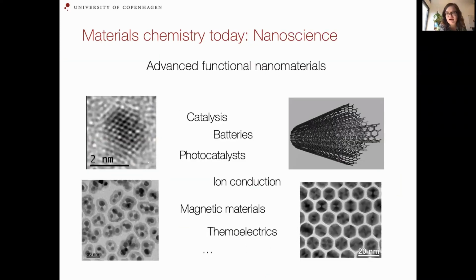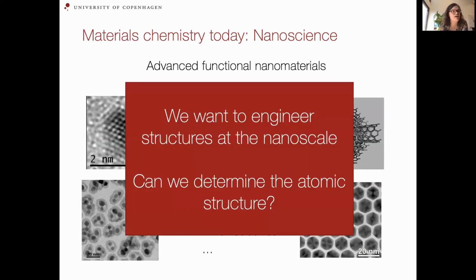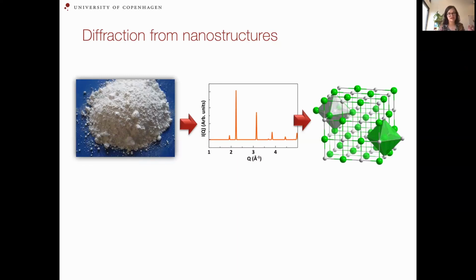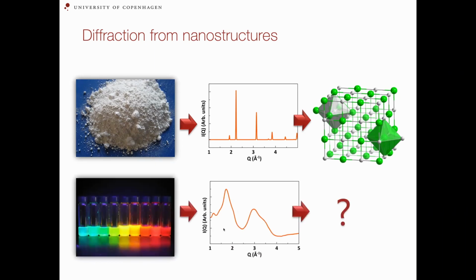Now, a lot of the materials that we are studying now, generally in materials chemistry, are nanomaterials. And we know that we can make different materials, and we know that we can make different properties. But of course, one of the issues is actually characterizing these. We can engineer structures at the nanoscale, but can we actually determine their atomic structure? Because it's this understanding of the relation between structure and properties that allows us to develop materials. The problem is, if I compare to diffraction, as is usually used for structural characterization from a bulk material, nanomaterials scatter something like this. So instead of these nice sharp Bragg peaks that we use in crystallography to characterize material structure, nanomaterials, here cadmium selenide nanoparticles, will give features like this, which can be much more difficult to extract quantitative structural information from.